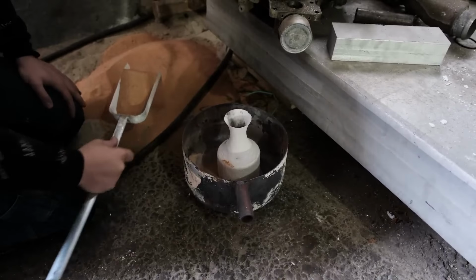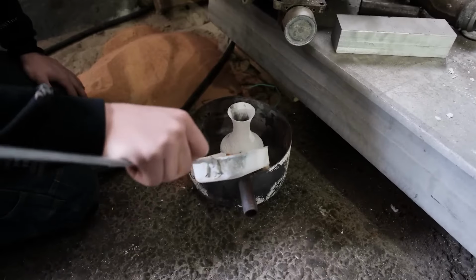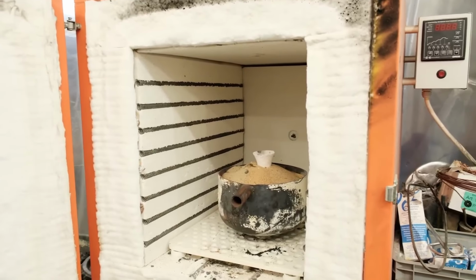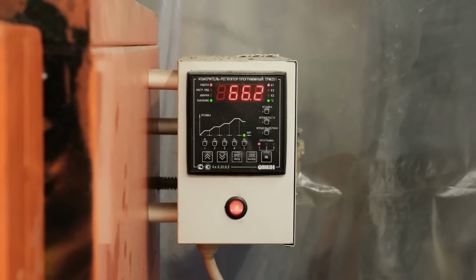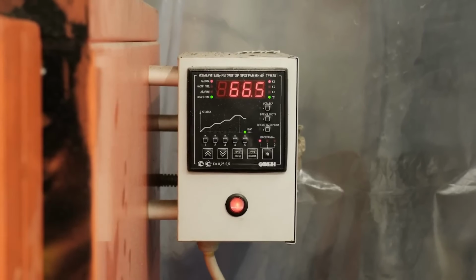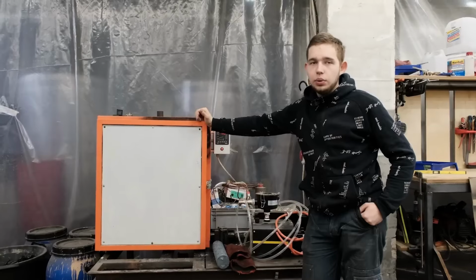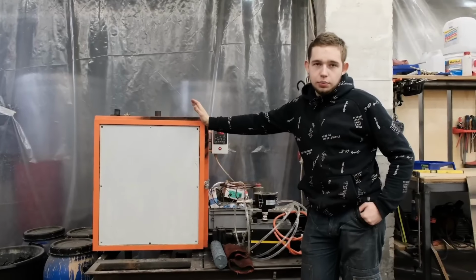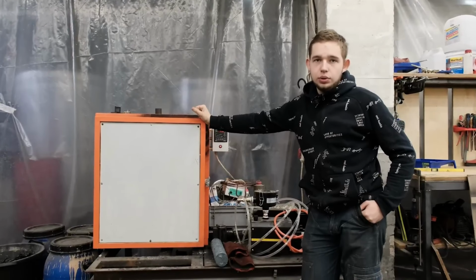The main thing is, what I really want to emphasize here, lift your hands so there's something to grab onto later. We've placed the sand-covered mold into the muffle furnace to heat it up to casting temperature, about 620 degrees. Now, we just wait for it to heat up, and then we'll pour in the aluminum.